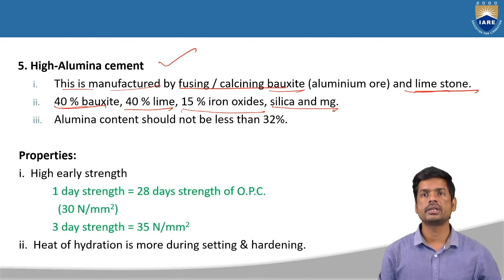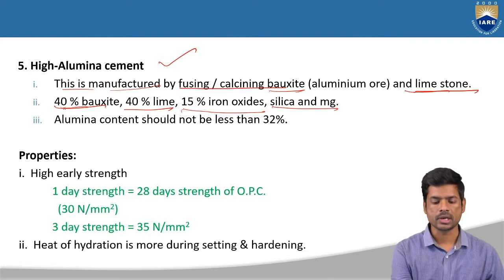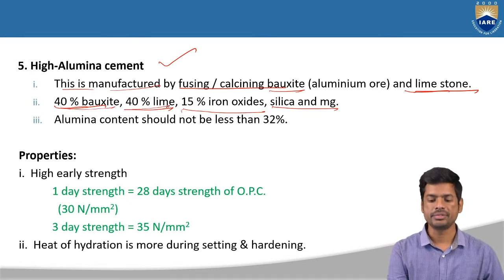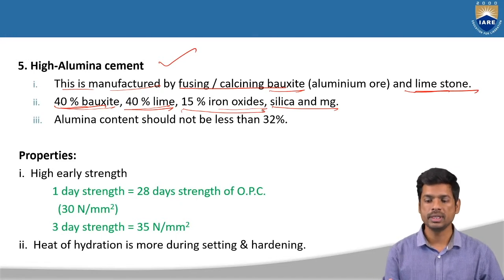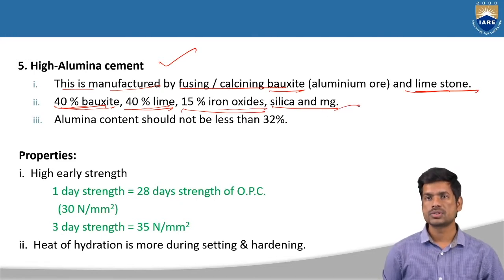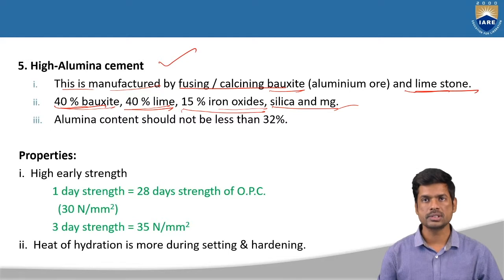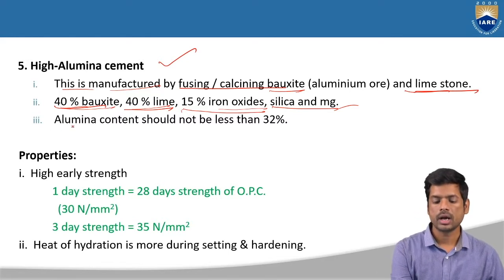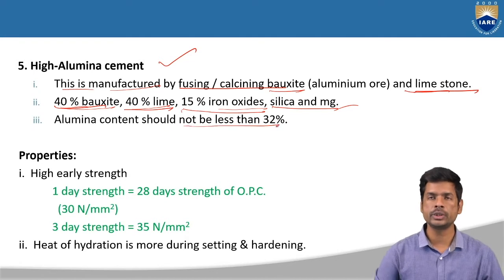These are the different chemicals we use for manufacturing high alumina cement: 40% bauxite, 40% lime, 15% iron oxides, and the remaining 5% silica and magnesium. By maintaining these compositions, we prepare the high alumina cement. And next, the alumina content should not be less than 32%.